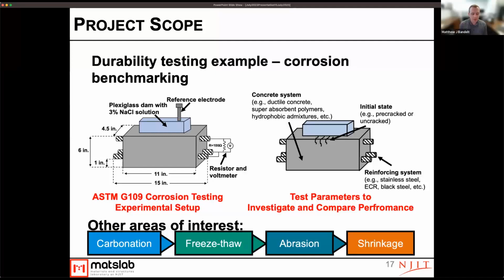That sodium chloride solution was applied in a cyclic manner where we applied the solution, we then allowed it to dry, we reapplied the solution, allowed it to dry, et cetera. And it was kept in a constant relative humidity environment that was basically designed to move the chlorides through the system in an expeditious manner.